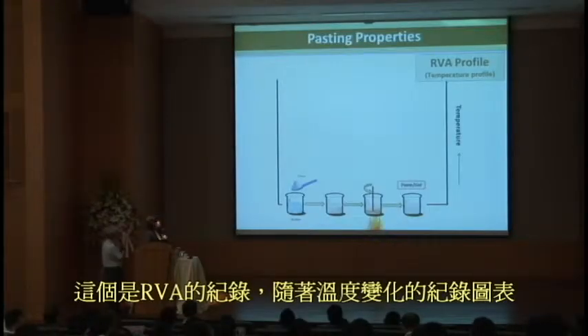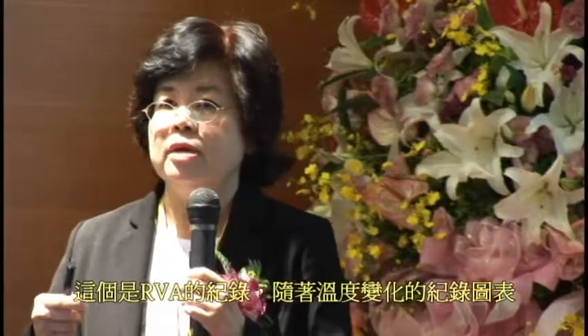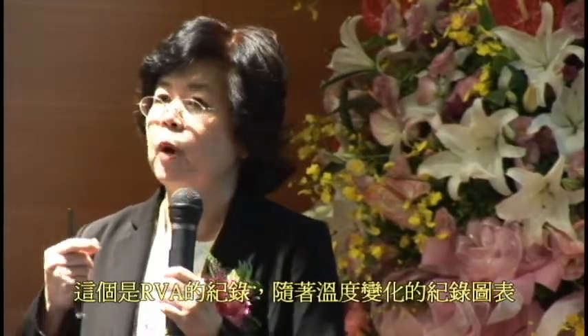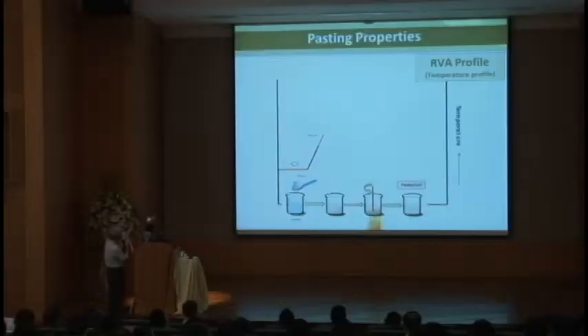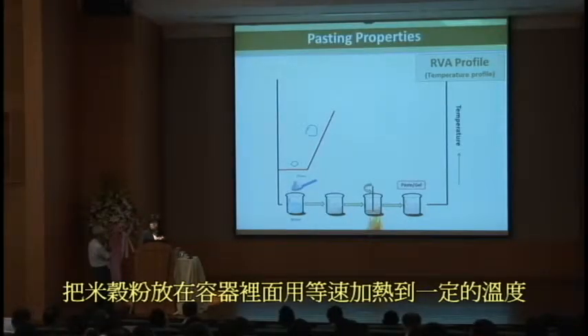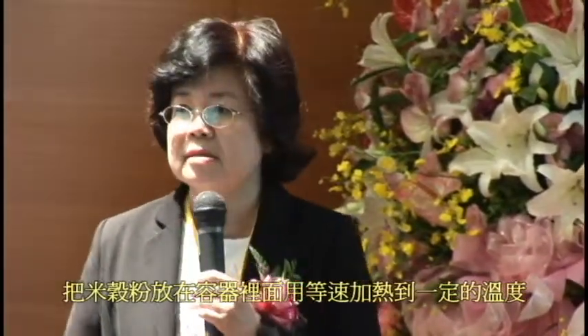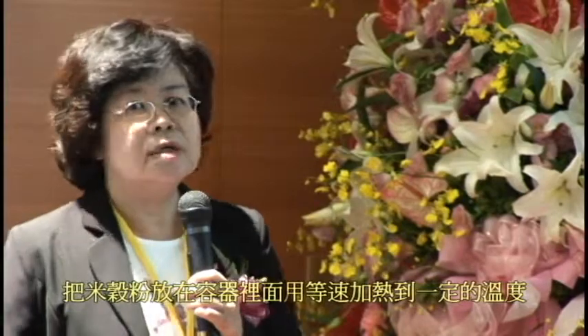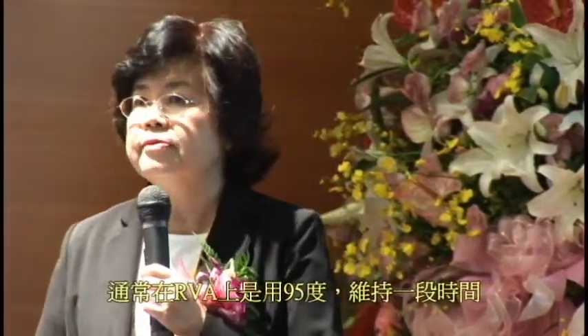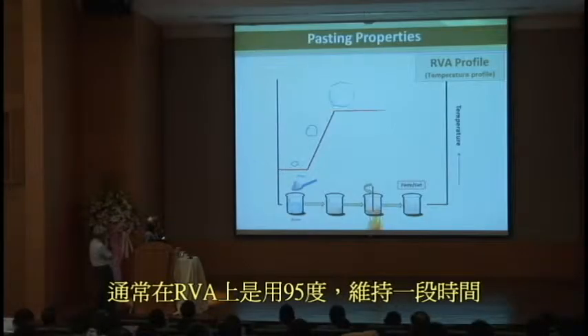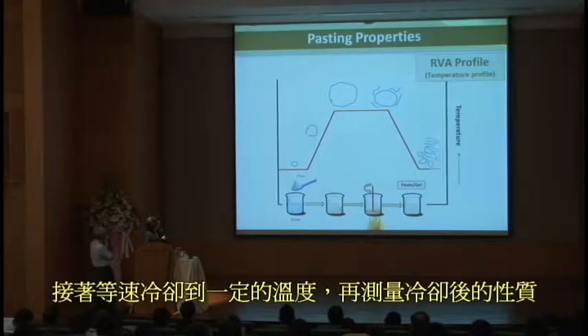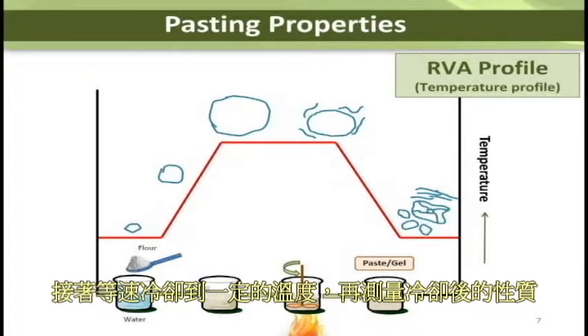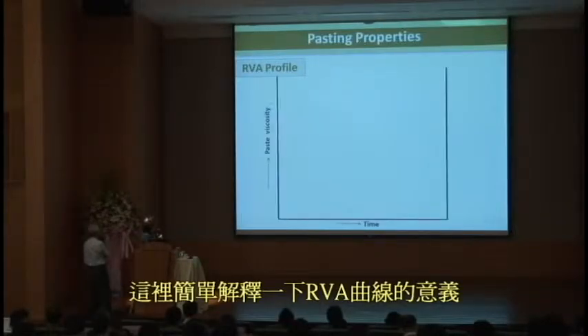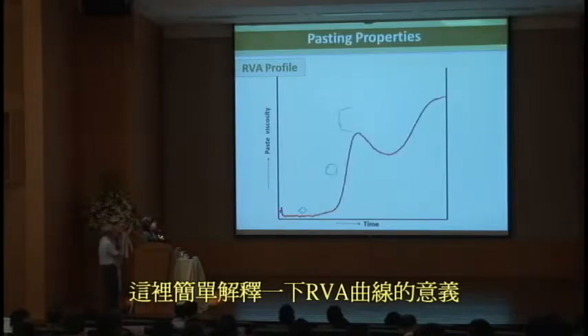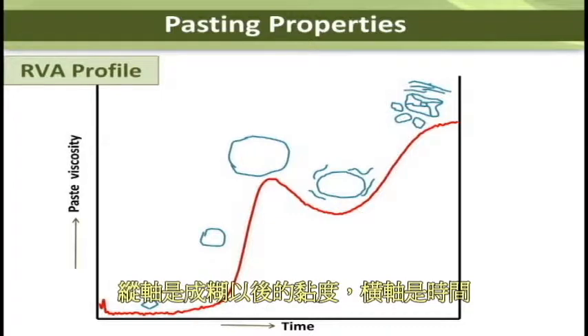This is a simplified temperature profile that we usually program in the RVA machine. We heat the flour slurry or flour suspension with a constant heating rate to a certain temperature, mostly 95 degrees Celsius, and then hold it for a certain time, and then cool down with a controlled cooling rate to a low temperature. And from the computer, we will get this profile. It is the pasting viscosity or RVA profile.